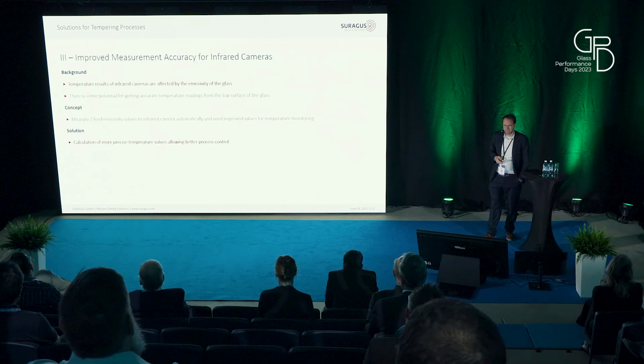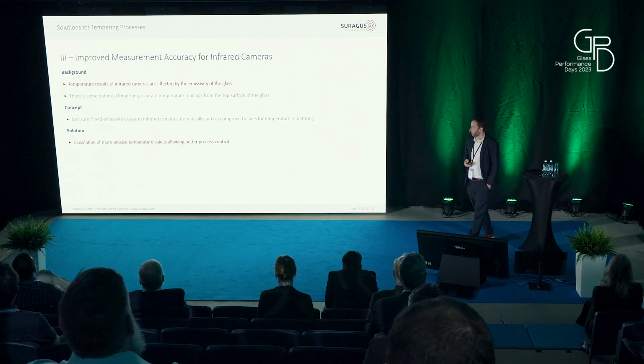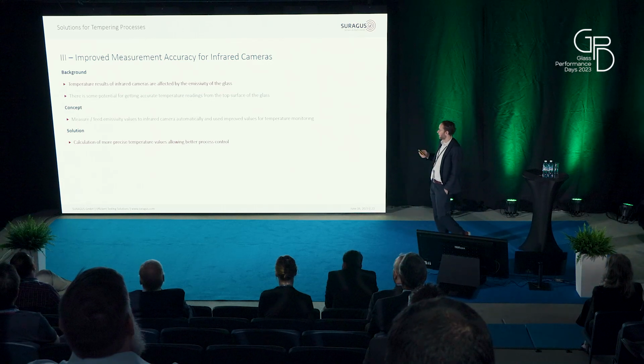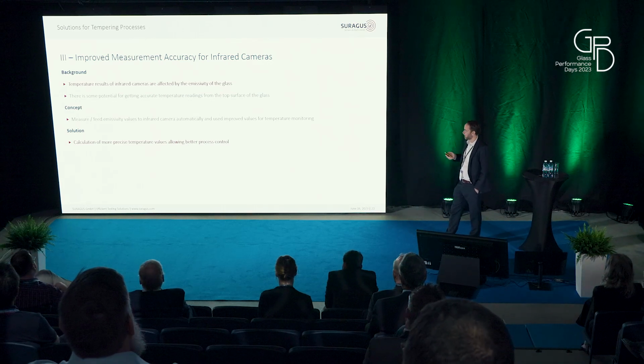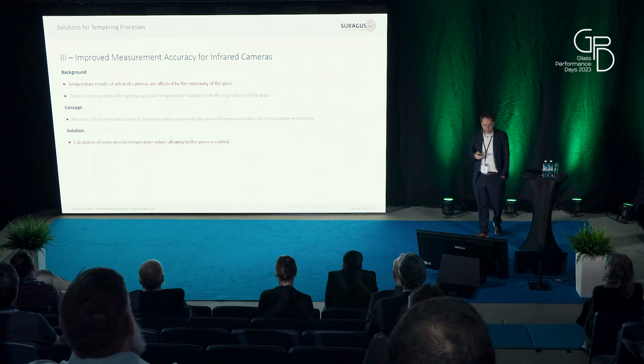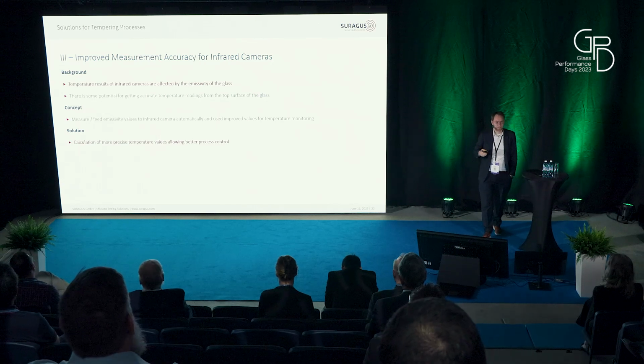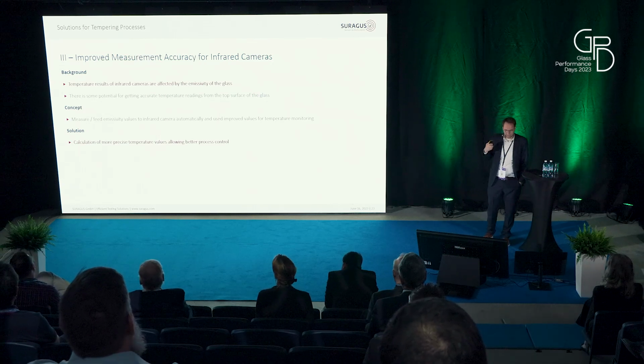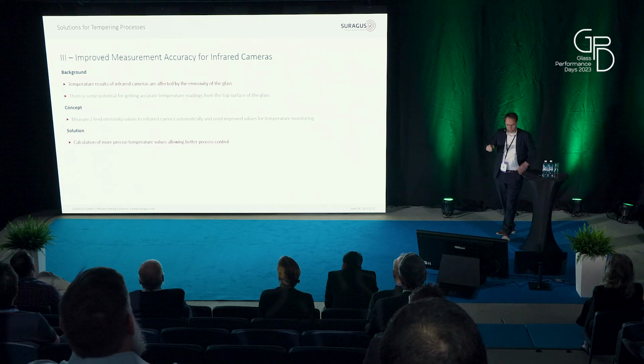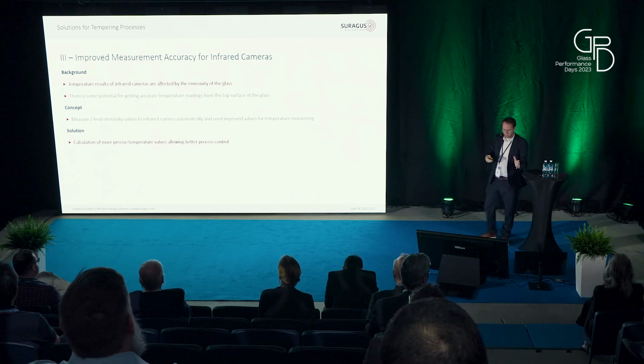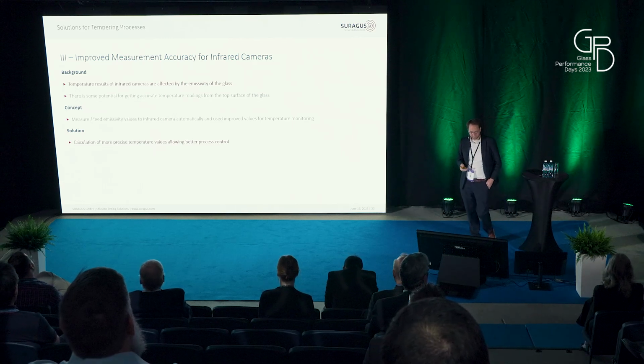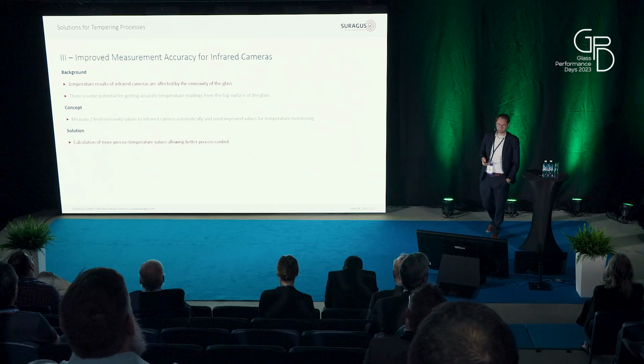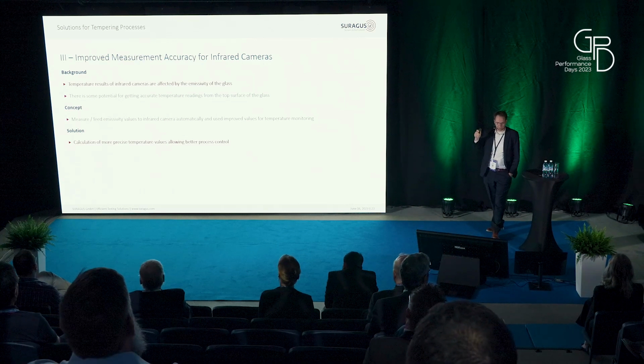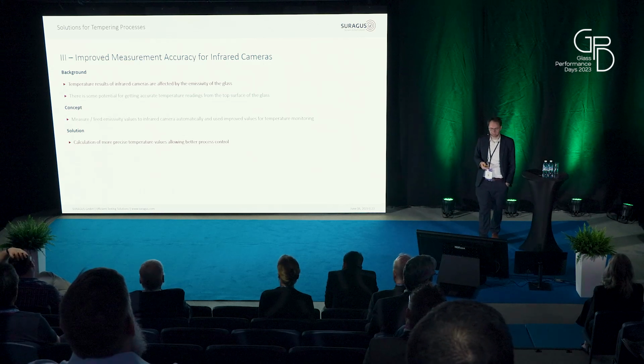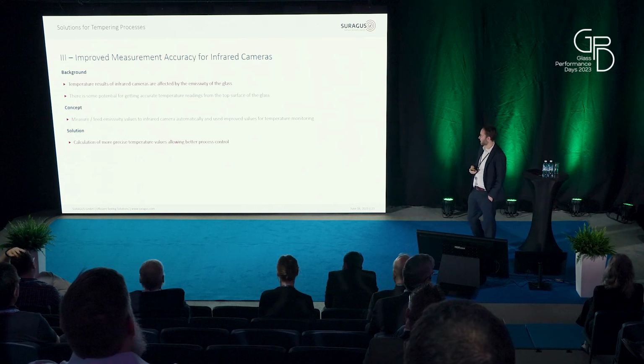The third one is that if you do infrared temperature measurements, then the emissivity of the glass affects the temperature reading. And since you use the temperature as a quality check, the distribution of the temperature for the assessment of your tempering process, it's also good to have a good temperature assessment, and the emissivity can also be fed into these infrared settings.